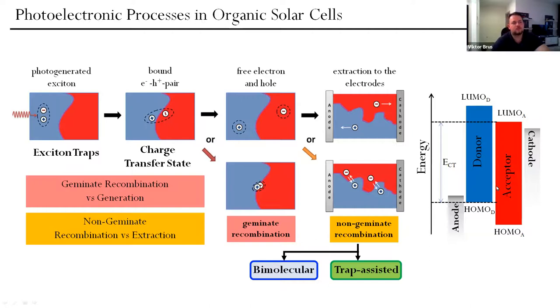So they are both organic semiconductor materials, but we cannot mix materials randomly. We need to first measure with UPS, or some other, like inverse photoelectron spectroscopy or ultraviolet photoelectron spectroscopy, for HOMO and LUMO values. We need to measure them experimentally and then see if there is enough discontinuity between LUMO, LUMO and HOMO, HOMO levels in order to split excitons efficiently. If these gaps will be too small, it will not be efficient to separate excitons and they will recombine. However, we cannot make too big gaps here because you see, they will define the effective band gap of the blend.